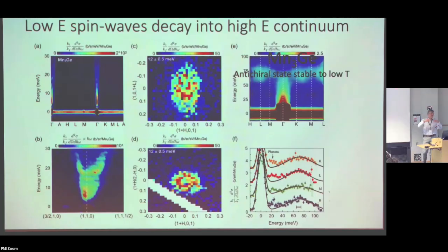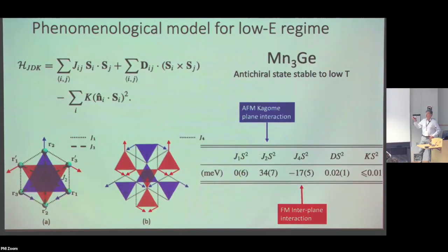So we cannot do a full fitting of these kinds of data, but just by extracting the gap and the velocities, we can get some information using the phenomenological theory of Chernyshov et al. And then we're able to see that it's actually this J2 interaction, which is interlayer interaction. Sorry, this is the in-plane Kagome interaction, antiferromagnetic, but then there's a ferromagnetic interplane interaction, which is equally strong, actually. These then give rise, along with the DM interaction, which also plays an important role, to the particular spin structure that is observed, which is an anti-chiral spin structure.